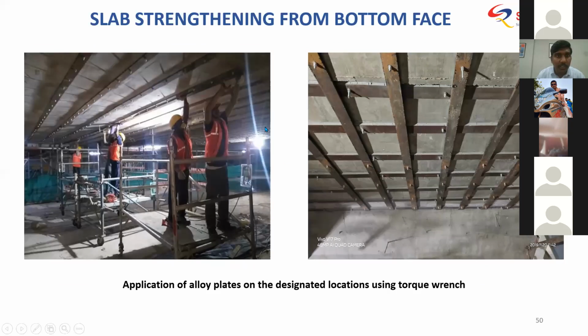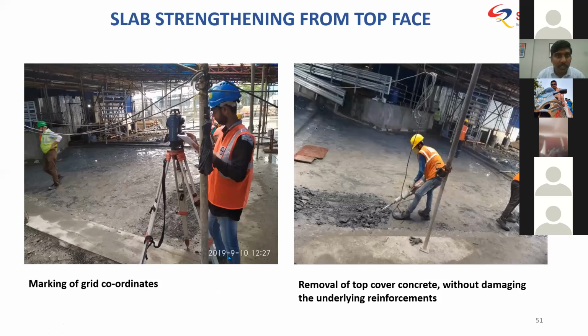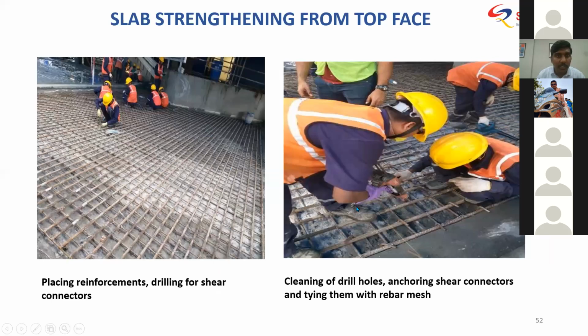Then on top of the slab, we went for conventional strengthening. So the cover concrete was removed. Mark the grid coordinates, and then the top cover of the concrete was removed. Just above the existing top rebar, we provided this new mat of RC steel, steel rebar, Fe 500 grade.